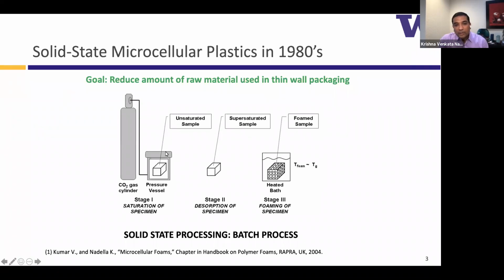In the first step, there's a pressure vessel. We put a solid plastic, typically an extruded piece of plastic, into this pressure vessel, expose it to high pressure carbon dioxide gas, and the plastic absorbs the gas from the environment into itself, slowly increasing its weight. You're typically absorbing somewhere in the 1 to 7% by weight of this plastic in the form of CO2 gas. Now, when you take this material out of the first step, you have a supersaturated sample that is sitting in atmospheric pressure and atmospheric temperature.